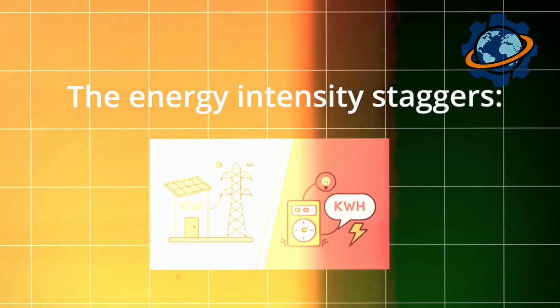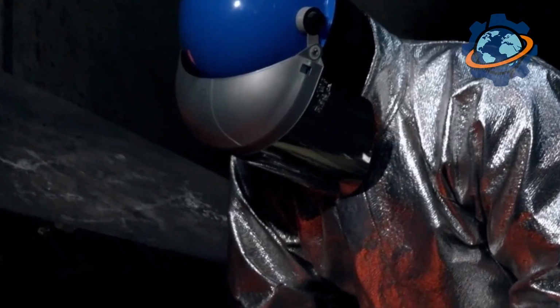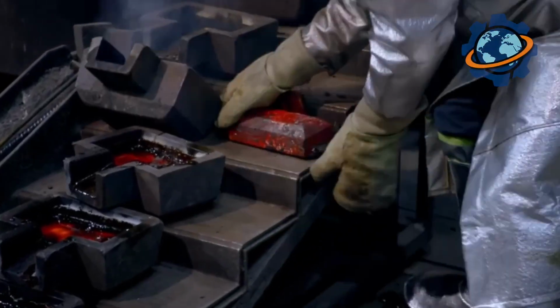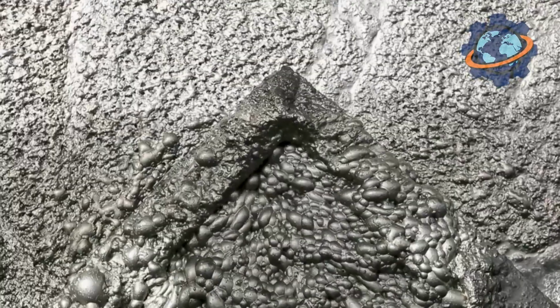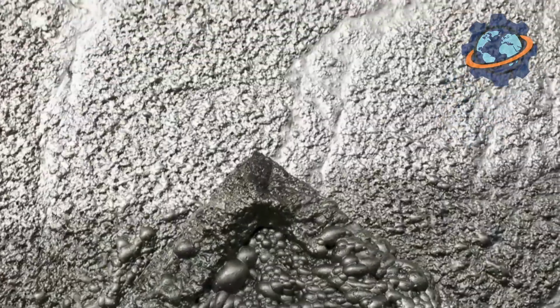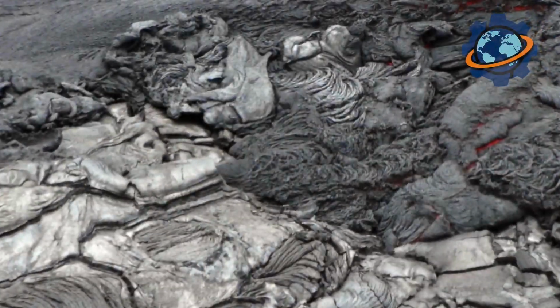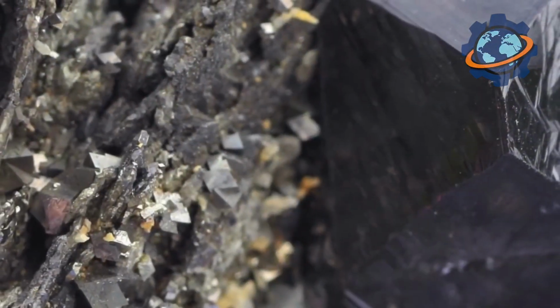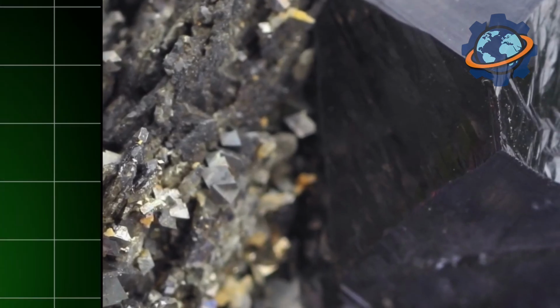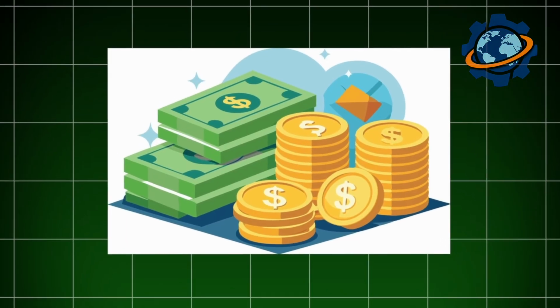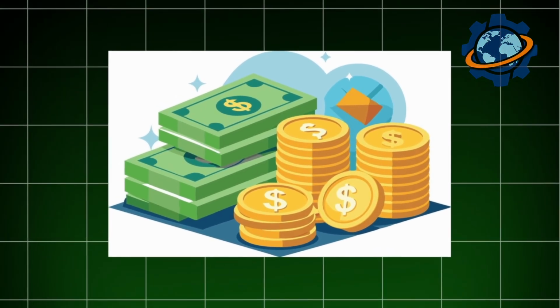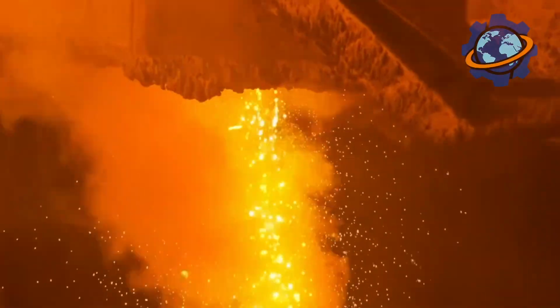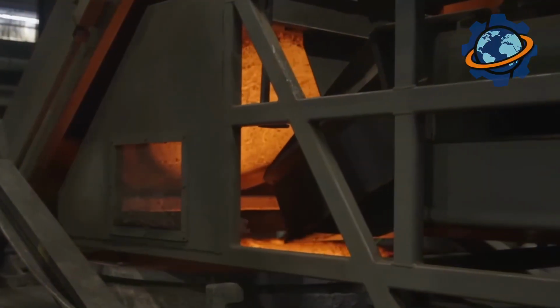Producing 1 ton of battery-grade nickel consumes 50 megawatt-hours, enough electricity to power average American homes for 60 days. This industry transformed radically in 15 years. Back in 2010, nickel prices averaged $7 per pound, used primarily for stainless steel. Battery applications consumed less than 5% of global production.